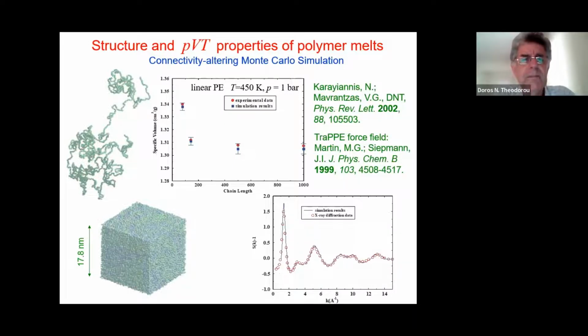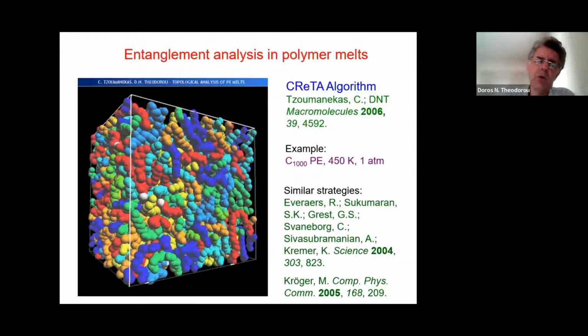The fact that we can equilibrate long-chain polymer melts means that we can also try to analyze entanglements between chains in these melts, because entanglements are very important in determining the rheological properties and the mechanical properties of large deformations. For this purpose, we and other groups have developed algorithms. Our algorithm we call CReTA, contour reduction topological analysis. It starts with a well-equilibrated configuration of the melt. It fixes the chain ends. For example, these white balls that you see here are chain ends of polyethylene chains.